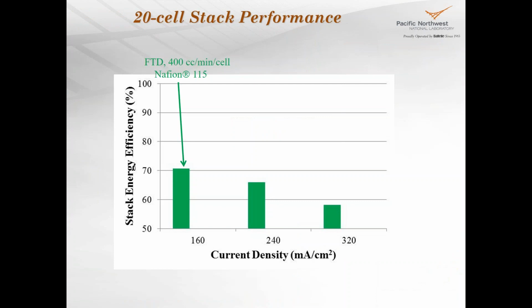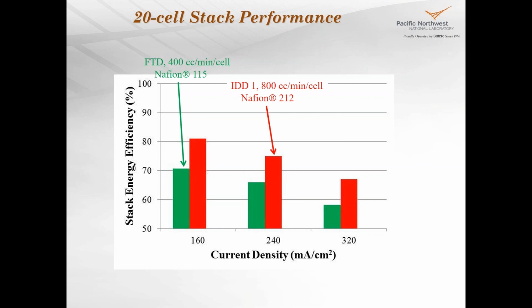So some of the performance parameters of this system. This showing here is the stack energy efficiency. Our first generation is a flow through flow field design. We're using Nafion 115, and you can see the energy efficiency here. The next design is an interdigitated design. With that design we can use a much higher flow rate, and we also use the Nafion 212. You can see a significant increase in the stack energy efficiency.